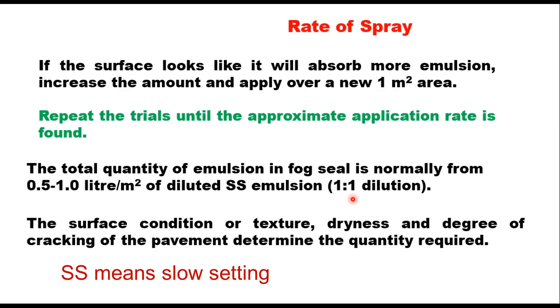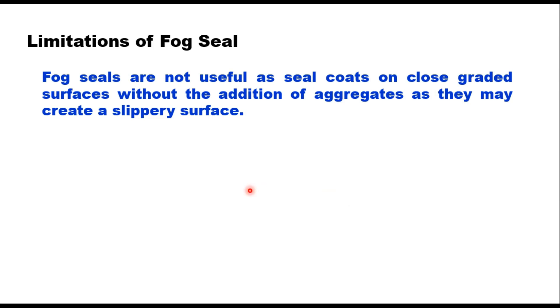The surface condition, texture, dryness, and degree of cracking of the pavement determine the quantity required. However, excessive application of emulsion must be avoided as this will result in pickup of bitumen by vehicles, leading to a slippery surface. There are a few limitations also — fog seals are not useful as seal coats on close-graded surfaces without addition of aggregate, as they may create a slippery surface.